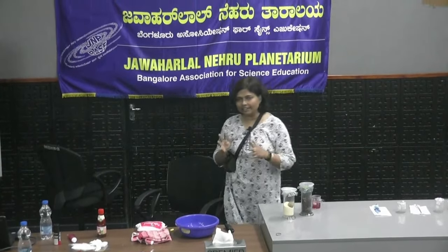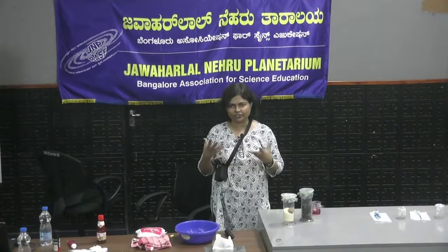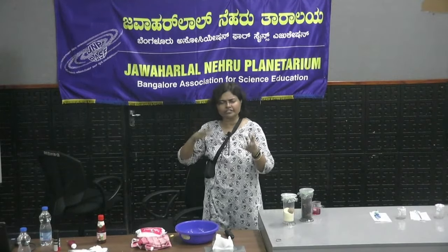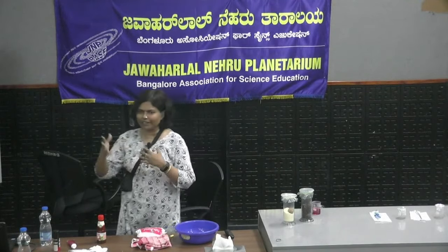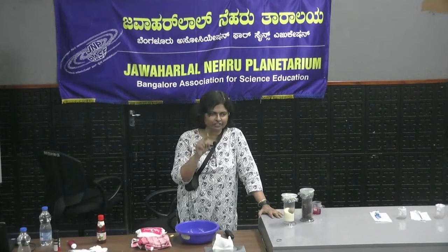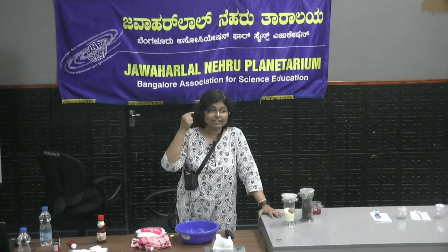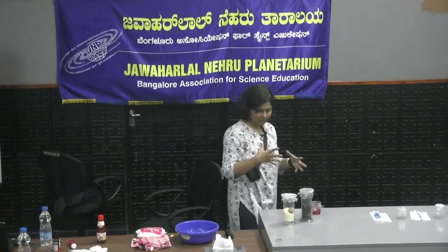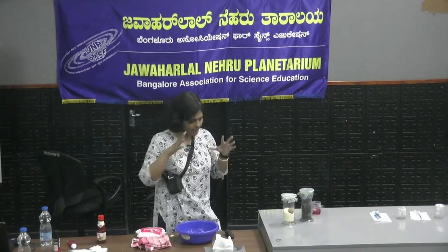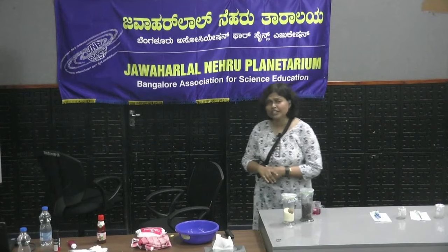So Sejal, they absolutely do, and that is because of their viscosity. Remember I told you that one of the parameters with which you can characterize soft matter is viscosity. For water, viscosity is constant, and like we mentioned, it's 1 millipascal second. For honey it would be more, for silicone oil it can be even lower or higher than water depending on the size of the oil molecule. But in the case of viscoelastic material, the coefficient of viscosity is not a constant for a given material. It depends not just on the rate of strain that you are applying, it also depends on the history of deformation. So if I take a material and apply a stress of 1 pascal on it, and if I take the same material and apply 0.5 and 0.5 pascals as two experiments one after the other, I'd get very different strain responses. So yes, they do store memory.